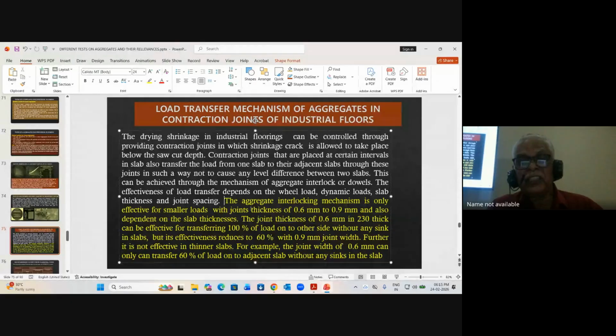Aggregate interlocking mechanism is only effective for smaller loads. So in special industrial floors, where only wheel loads, parking etc. is there, and the joint thickness is 0.6 mm to 0.9 mm depending on the slab thickness - the joint thickness of 0.6 mm in 230 mm slab thickness can effectively transfer 100% of the load to the other side.